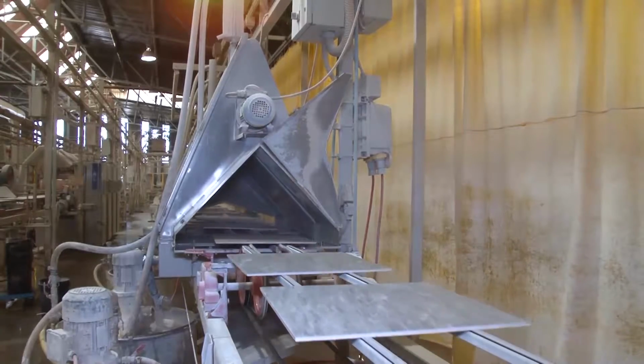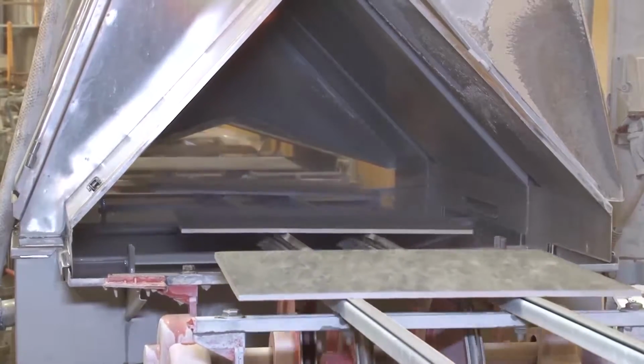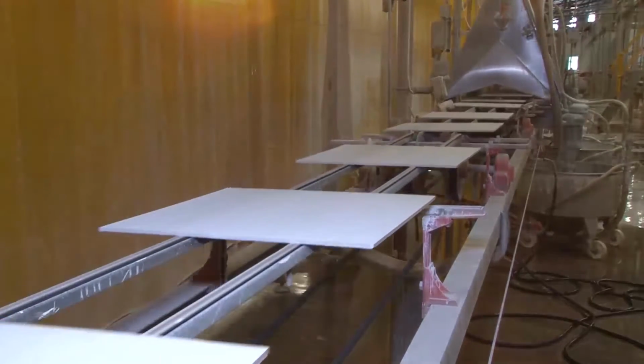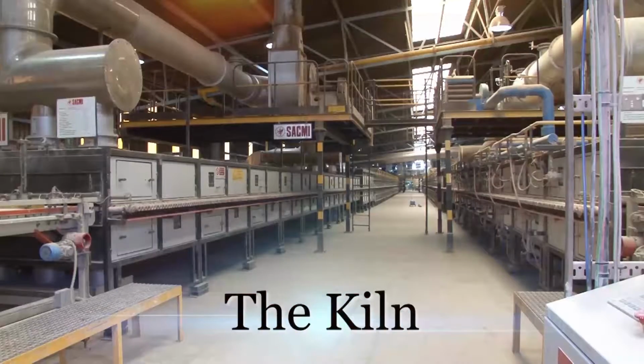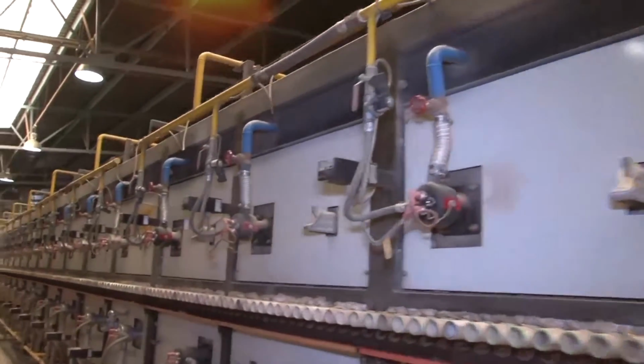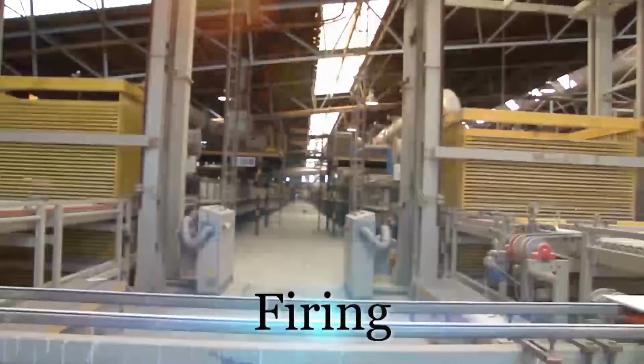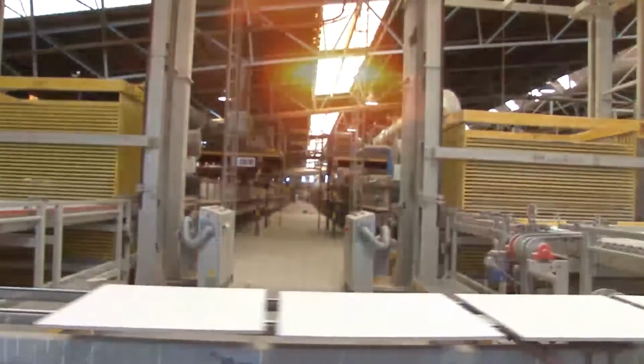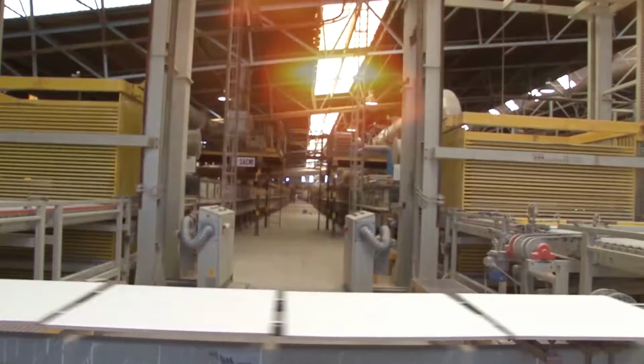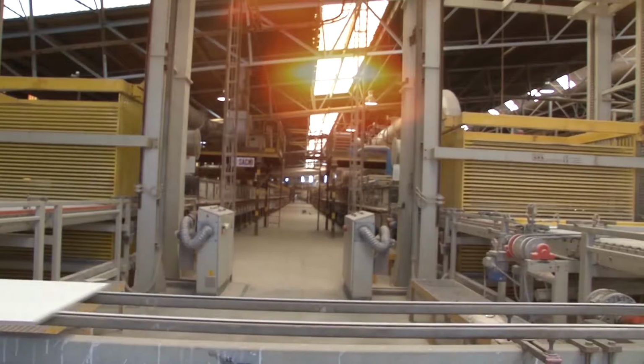A protective top coating of glaze is sprayed onto each tile. This turns white shortly after it comes out of the spray tunnel, but will become transparent as the tile passes through the firing process in the kiln. The kiln is a long tunnel heated by gas heaters through which each tile passes in a process known as firing. In the first section of the kiln, the tile is dried at low temperature to remove water from the clay. If the tiles were subjected to very high temperatures in this first phase, the water in the tiles would turn to steam, and many of the tiles would explode.